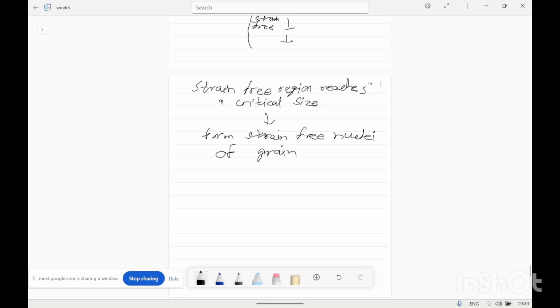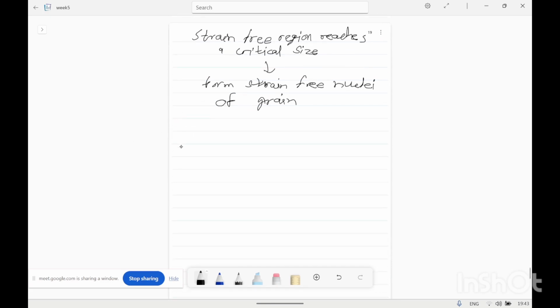Second is the strained grain. Like if we see the two grains A and B, this is the low strain, this is high strain. So there is an energy gradient present at this grain boundary. Due to the energy gradient, the low energy region boundary starts to bulge into the high strain region. This bulging leads to nucleus of strain free grains.